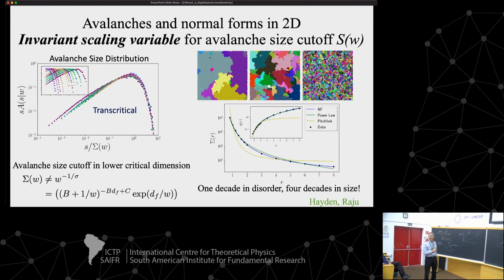They never collapsed. So the first thing that Lorian did was he did it on a random lattice. And that made all the shapes look like one another, and we could now take this raw data. These are the avalanche area fractions. And she could now, since they were the same shape, collapse them, and the data points showed how much they had to shift the sigma of W to collapse. And then you could fit all the data with our formula.